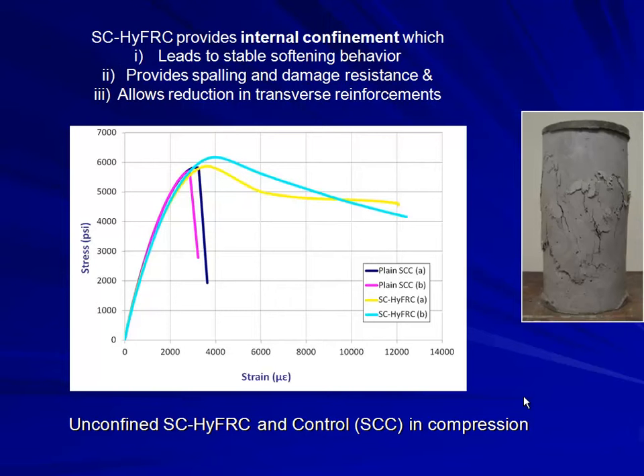So what you see here is the self-consolidated hybrid fiber reinforced concrete we used for the bridge columns. Right here, this is the hybrid fiber reinforced. This is just a control, a self-consolidated concrete, but no fibers. And you can see definitely the difference here, that you have a very stable softening behavior in this hybrid fiber reinforced. And of course, this allows you then to look at damage.